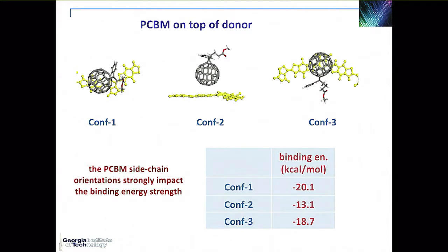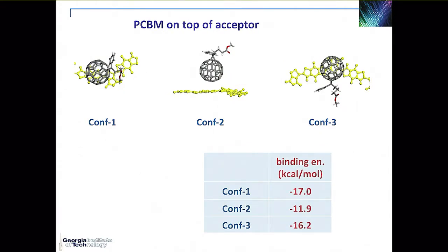So again, we see that the PCBM side chain does indeed, the orientations of those side chains with respect to the backbone do strongly impact the binding energy strength. In the case of PCBM on top of the acceptor, even in the case of that configuration, there is indeed an increase from 12 to 17 kilocalories per mole. So again, a significant increase, but not as much as when the fullerene was on top of the donor.